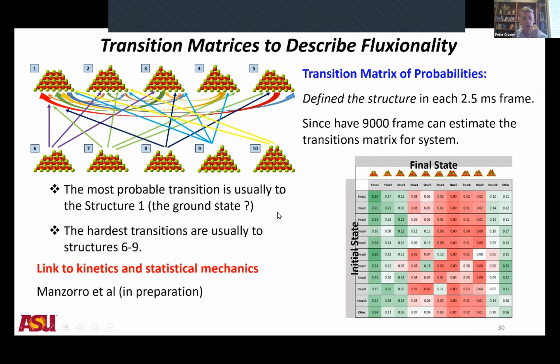And just for ease of viewing, we colored the high transition probabilities green and the low transition probabilities red. If you look at the green column here, this is all associated with transitions into structure 1, which is what we might call the ground state. So everything likes to transition into structure 1. Whereas if you look at these columns over here, transitions into structures 6 through 9 are much less likely, because they actually involve these adatoms.